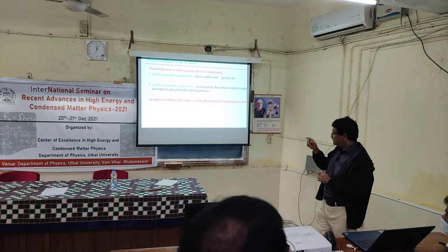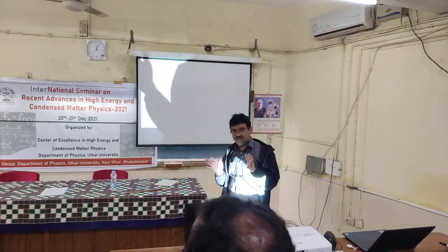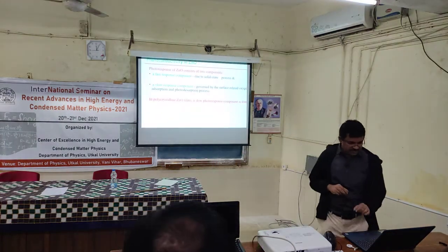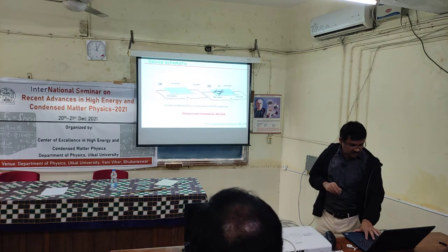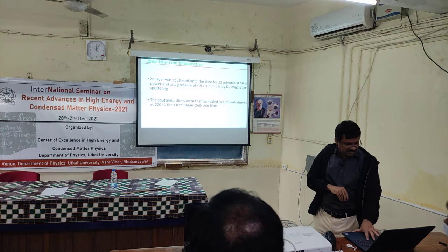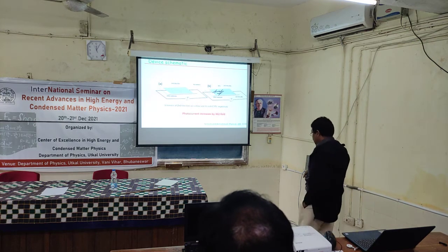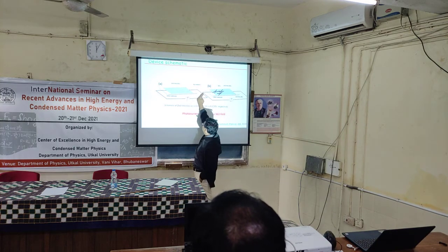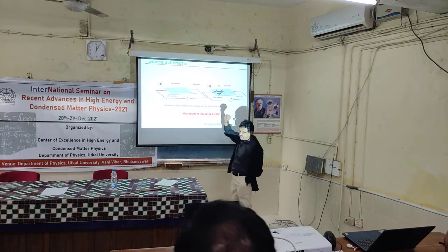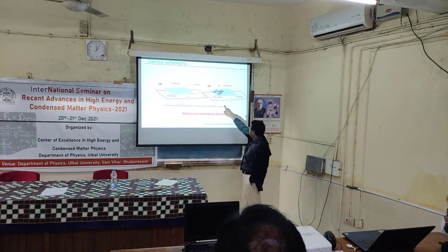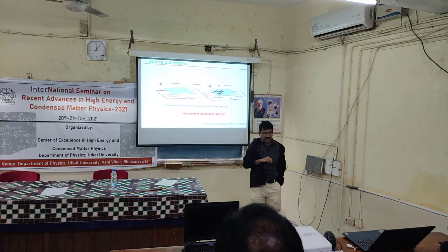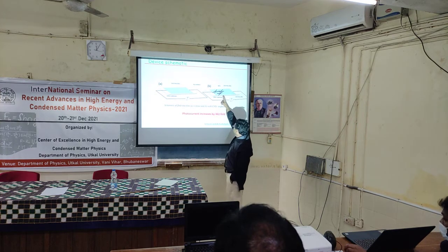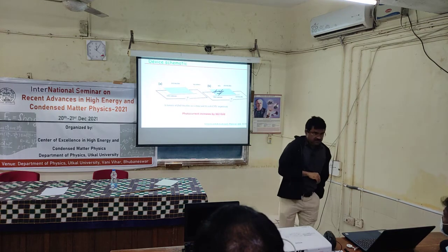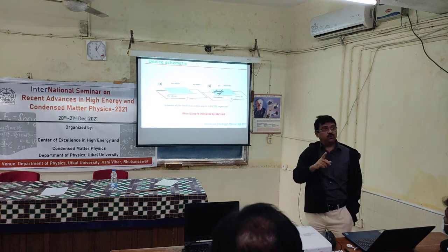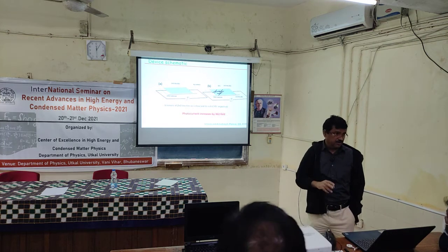I'm not going to deal with that in this context. What we have done here is look at how we can suppress the recombination of charge carriers. We deposited zinc oxide again, and afterwards we took carbon nanotubes. This is the zinc oxide thin film connected with two silver contacts. Apply a bias, get a current, and you see the photocurrent. Now we have sprayed carbon nanotubes over one side of the zinc oxide film, not completely. In that case, we are able to enhance the photocurrent manifold, maybe 10 to the 3 times.